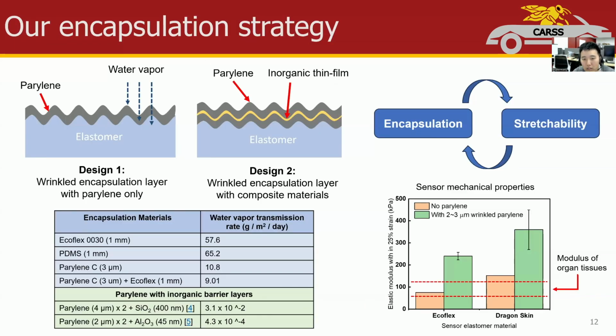We also characterized both the sensor's encapsulation and mechanical properties in order to have a good balance between them. Here, we first measure the water vapor transmission rate through different materials. We can see on the bottom table, the EcoFlex and PDMS elastomer can have large water vapor transmission, but 2 to 3 micron Parylene can reduce it significantly. However, this thickness is still too thick.